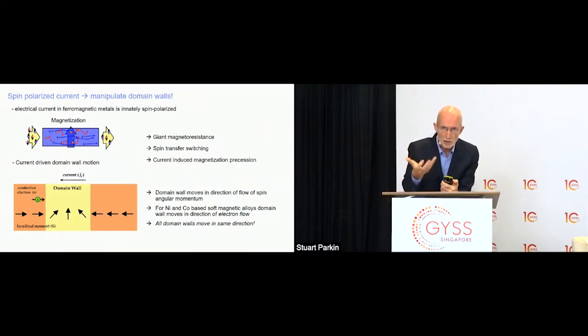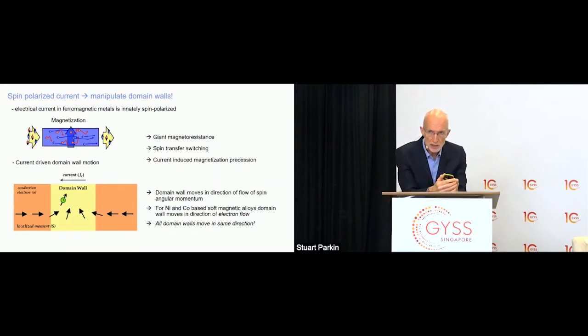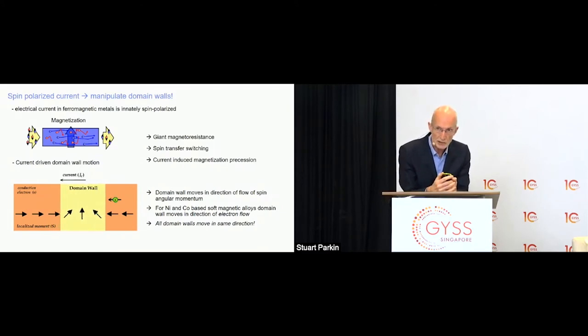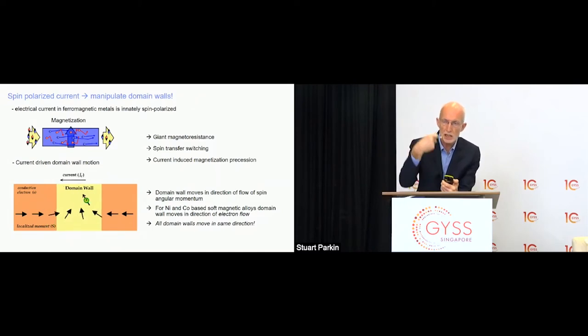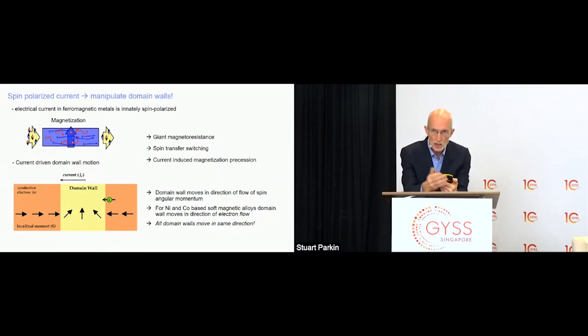Just as I said before, if you take current from a battery with equal numbers of spin up and spin down electrons in a magnetic material magnetized in the blue direction here, the current becomes spin polarized due to spin dependent scattering. But because an electron with a spin has a spin angular momentum, and angular momentum is a conserved quantity, as you can see in the schematic cartoon below, in a racetrack formed from this orange material, a domain wall is shown here between two orange regions magnetized to the right and to the left. A conduction electron passing through this domain wall with a spin in a given direction, as it crosses the domain wall, would adiabatically change its orientation as it follows the magnetization within the wall and would deliver a quantum of spin angular momentum to the domain wall.